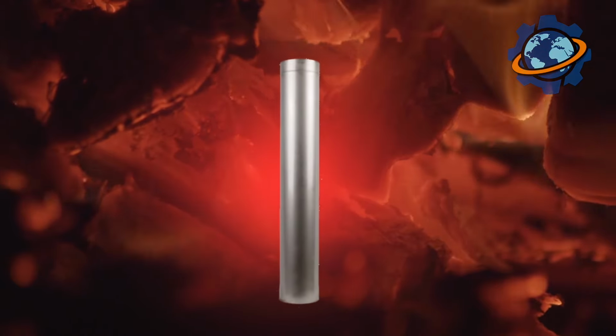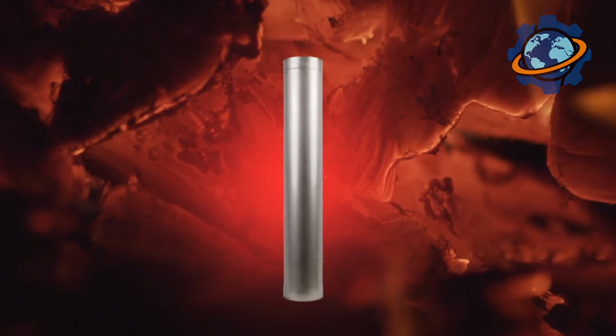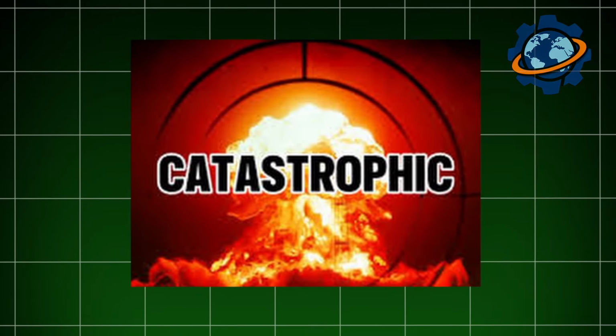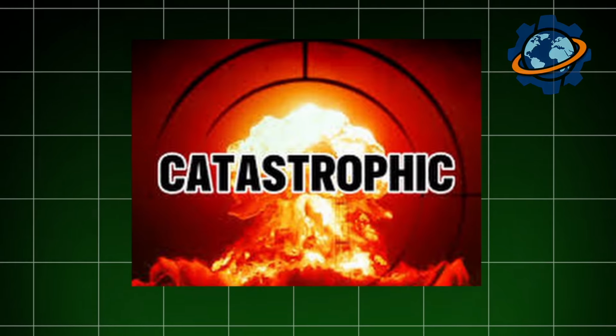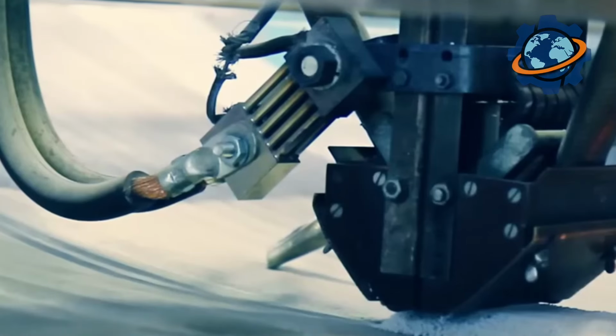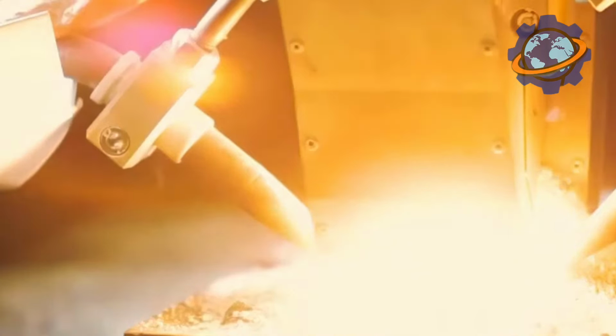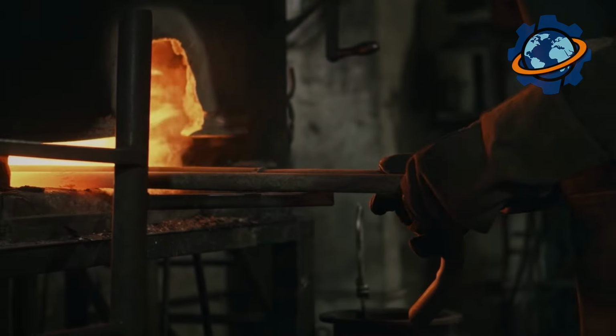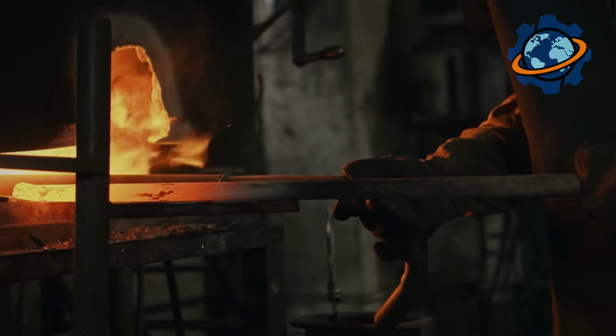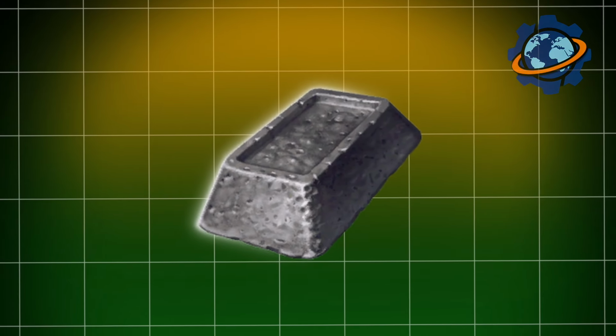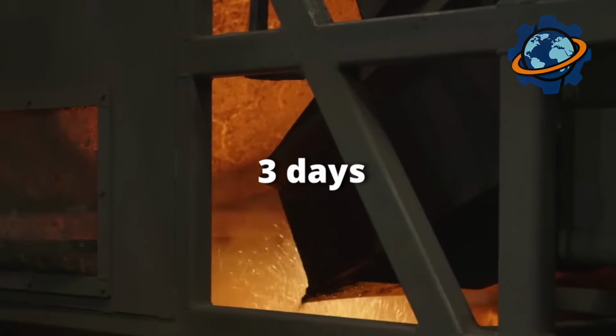This cooling phase determines everything. Cool too fast, thermal stresses create internal cracks invisible to naked eyes but catastrophic under reactor operation. Cool too slow, large crystals form, weakening the structure. Thermocouples embedded throughout the mold measure temperature at 300 points simultaneously. The ingot shrinks 5 inches in diameter while cooling, enough movement to crack the mold if thermal expansion isn't calculated precisely. Workers strip the mold after 3 days, revealing a steel cylinder glowing dull red at 800 degrees.